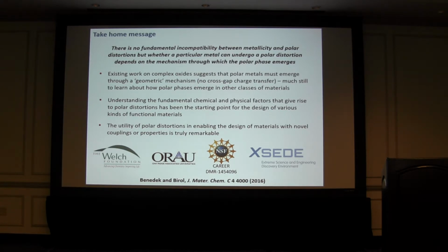Okay, but it wouldn't be zero if you had free carriers around. No, then you don't have. Well, but first of all, you're saying even before adding carriers, you're saying the effect is dominated by the Z star. This is true only for longitudinal phonons, but the ones which are responsible for the transition are the transverse ones.